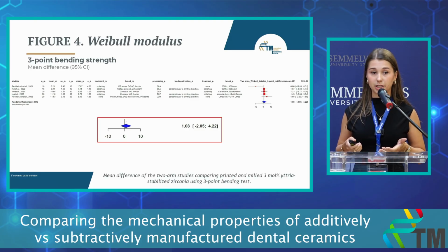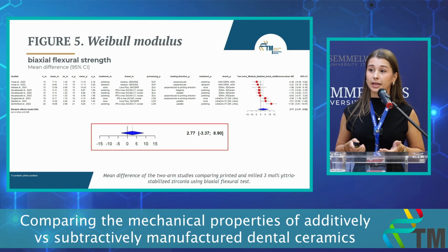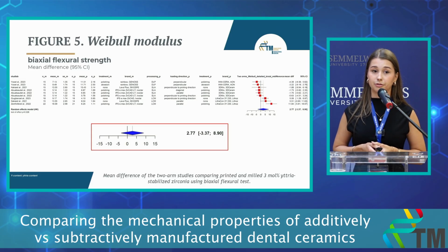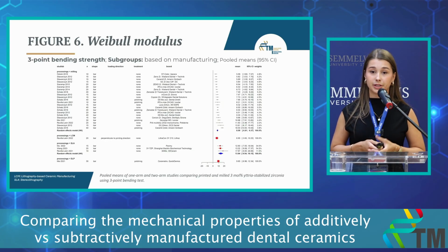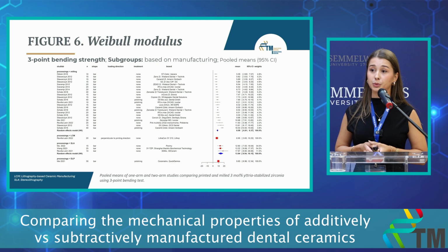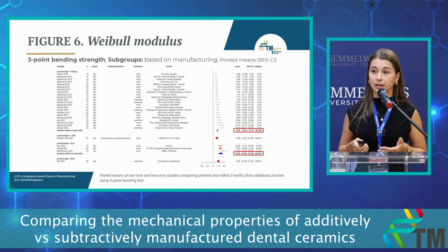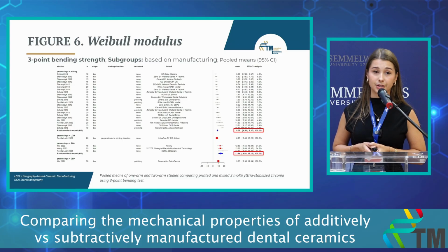This is a dimensionless parameter, and it basically shows us that the reliability is the same between the milled and printed zirconia. Again, we have a higher value to this Weibull modulus with the materials measured with biaxial flexural strength. Still, it isn't clinically relevant, and this indicates that printed and milled zirconia have similar reliability. We included again many one-arm studies where we are working with pooled means, and if we look at the data, we can see that LCM-produced zirconia, which is a printing method, is significantly more reliable than milled zirconia.